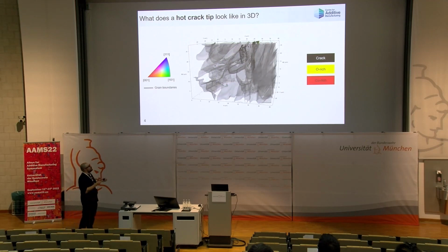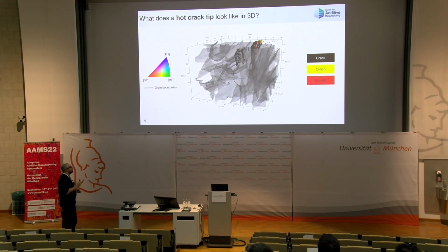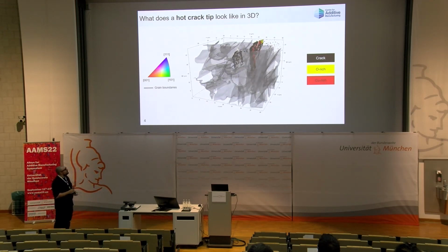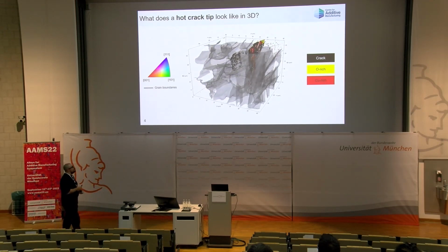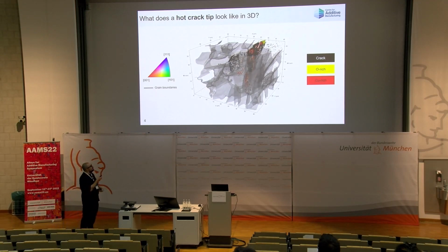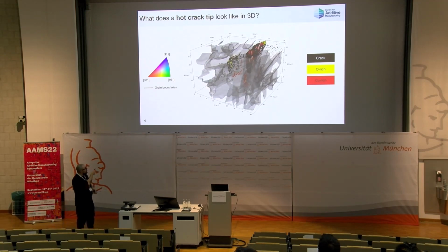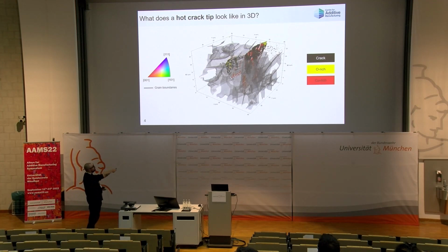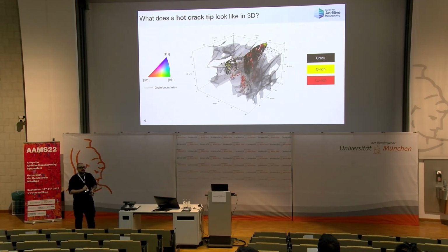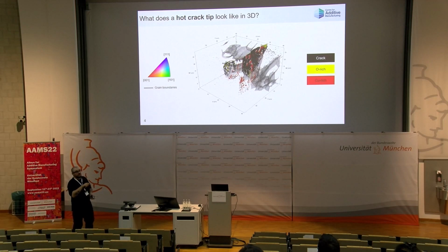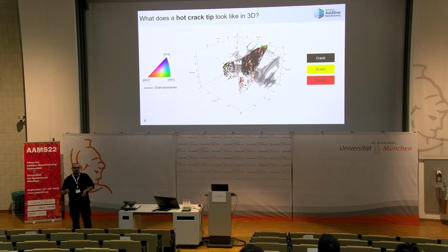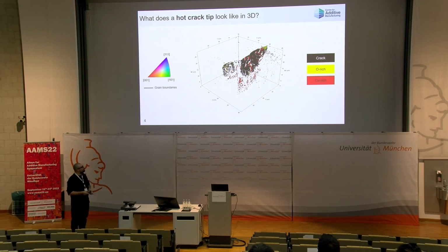When we look at the L-PBF sample, what we can see is that hot cracks are found, of course, at grain boundaries, and we were aware of that, but also we can find a peculiar segregation of alloying elements. Specifically, this alloy is copper-rich, so what we can see here is the presence of copper-rich phases near the hot crack tip. And we are 100% sure that this is a hot crack, also because we can see some oxidation, which is known to be a clear effect of a crack formed at high temperature.